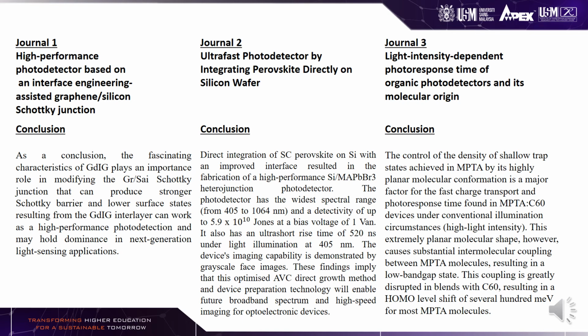Direct integration of single crystal perovskite on silicon with an improved interface resulted in the fabrication of high-performance silicon MAPbBr3 heterojunction photodetector. The photodetector has the widest spectral range from 405 to 1064 nanometer and a detectivity of up to 5.9 times 10 power of 10 Jones at a bias voltage of 1 volt. It also has an ultra-short rise time of 520 nanosecond under light illumination at 405 nanometer.